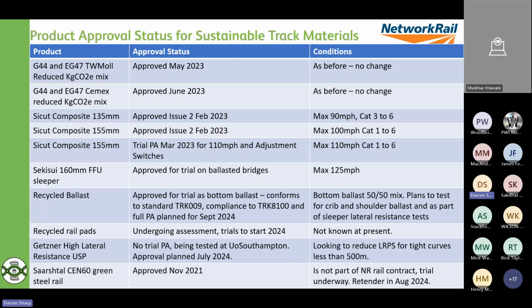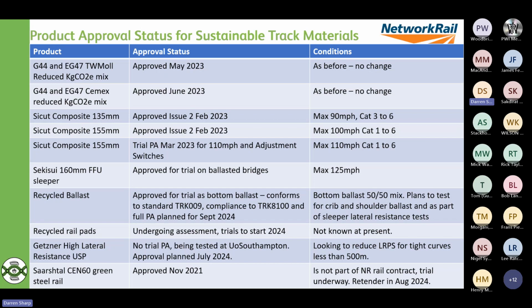Sekisui 160mm FFU, so that's the FFU Sekisui sleeper bearer, the bearer that we used at Newark. That's also approved for trial on ballasted bridges up to 125 miles an hour. So that at the moment is our forefront high-speed composite sleeper that we could use. That's going to be gaining approval prior to the hardwood composite phase out.